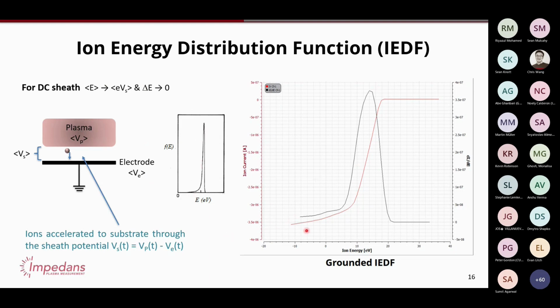And this is sort of a data example. So the idea is that it's sitting on a grounded electrode. All your ions have some sort of distribution, and the center of this distribution is pretty much the plasma potential. Well, actually, maybe the upper end of the distribution is the plasma potential. So say, for example, if there are collisions in the sheath, if the pressure is high enough that there can be a collision before you reach the sensor, it will, on average, bring the energy down from the plasma potential. But let's say in a perfect vacuum or ideal situation, all the ions will be centered around the plasma potential. Okay, so that gives you information about the plasma, which is quite valuable.